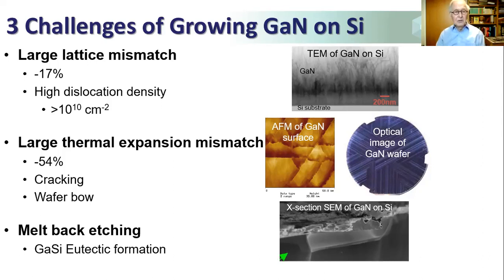The second problem is this extremely large thermal expansion mismatch between gallium nitride and silicon. The thermal expansion mismatch is 54%, which is huge. And you grow these devices at about 1,000 degrees centigrade. So when you cool down from this temperature, the gallium nitride is in tension and it cracks.